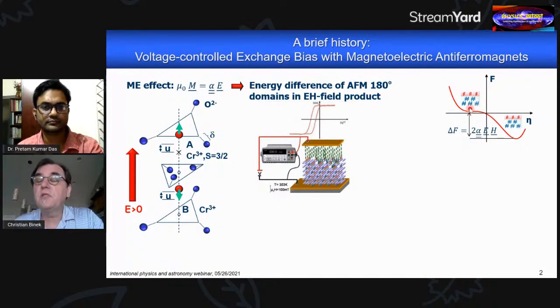And what we see here in this cartoon also is something I should mention because it's important. You see here in pink some spins that point always in the same direction. This is not a material yet that I deposited on this antiferromagnet. It is a property of the antiferromagnet itself, which we call boundary magnetization. That's a robust magnetic moment that appears at the surface of materials such as chromia that have these type of symmetry conditions. That's a finding of my colleague at UNL, Kirill Belashchenko, who experimentally found that these magnetoelectric antiferromagnets, when they are in a single domain state, have this robust property of boundary magnetization.